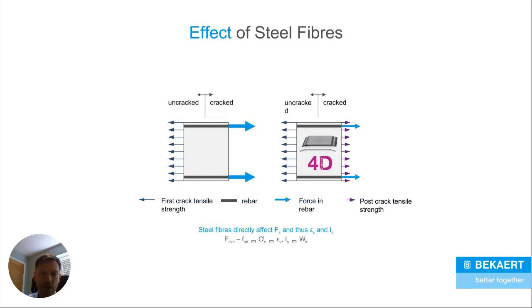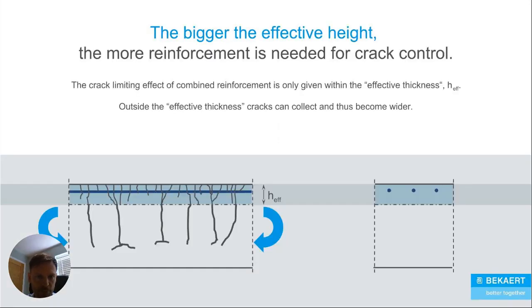At some point, the concrete will crack. Okay, and in order to get a calculated crack width in your concrete, it's dependent on the stresses in the steel. So the addition of fibres to that concrete mix decreases the stresses in the rebar, allowing a reduction of the rebar that you need in order to get a defined crack width calculation.